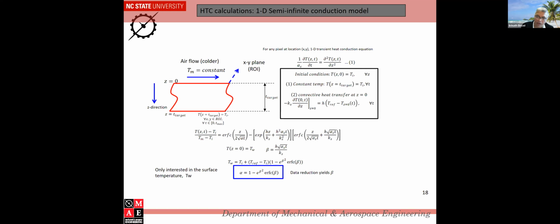into the plane, into the wall, and we apply the initial condition that everything is at initial temperature, and then at the wall we have the convective heat transfer, and down way deep away from the wall, the temperature doesn't change because we are using plexiglass. There is no conduction, so it's called a semi-infinite wall. So you basically won't see heat transfer go through the wall. It only stays at the skin of the wall.